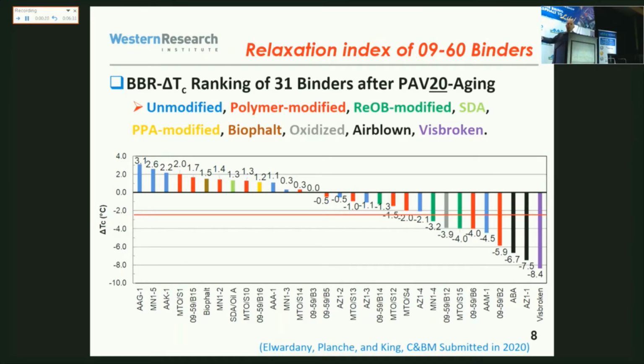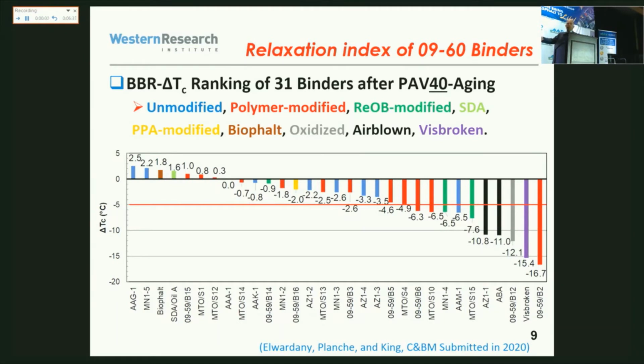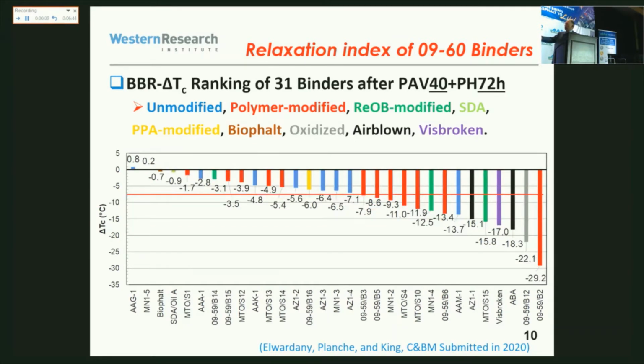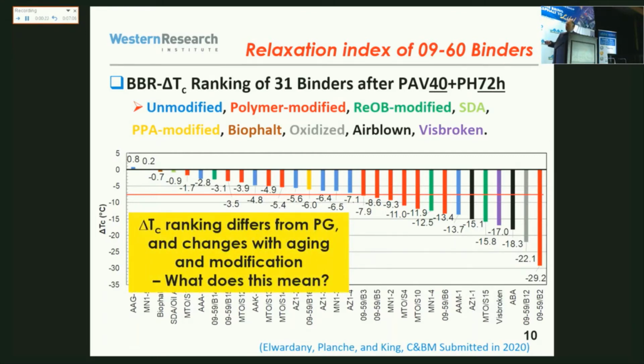And that's after 20 hours PAV aging. And if we go to 40 hours, the ranking keeps changing. And if on top of that, after 40 hours, we also include physical hardening, so long-term conditioning for 72 hours at low temperature, that changes again. So there are lots of things going on. And the ranking that we have now has nothing to do with the early one with just PG specification. So we see a lot of changes, particularly with aging and also with polymer modification. But what does this mean? Is that something that we should worry about, or is this important, and how can we explain those changes? So that's what a big part of the project was about.